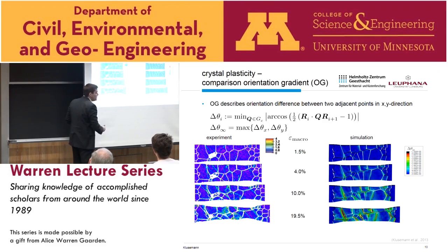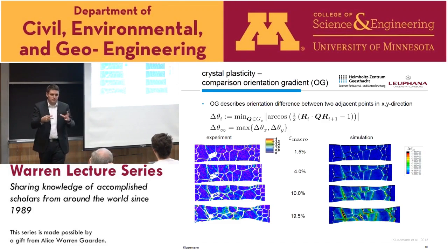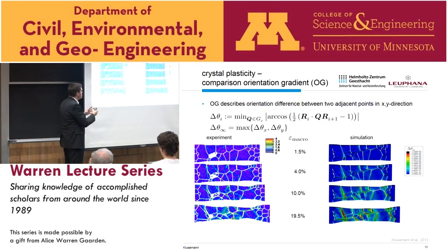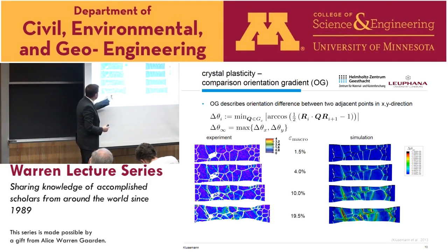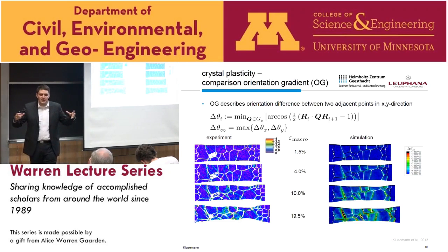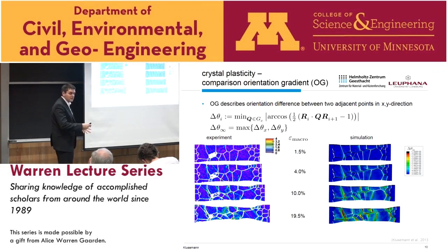And interestingly, in this region where we saw the necking kind of behavior, the largest contraction behavior, we nearly didn't see any orientation gradient developing, which implied for us at least that there might be some hardening mechanisms related to dislocations, so geometric dislocations, that take place in this region, where this part is softer than the remaining part, and we would get there kind of stronger contraction.